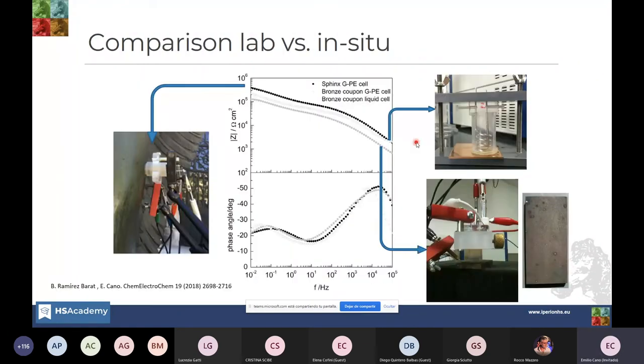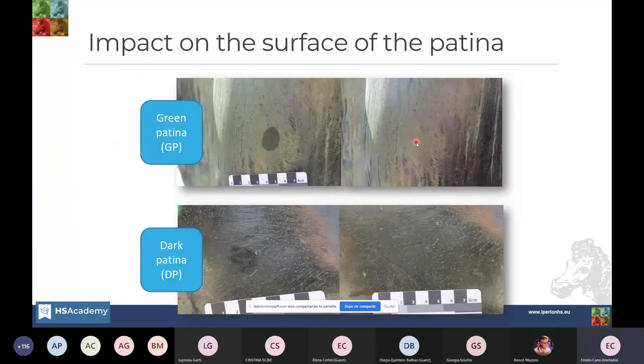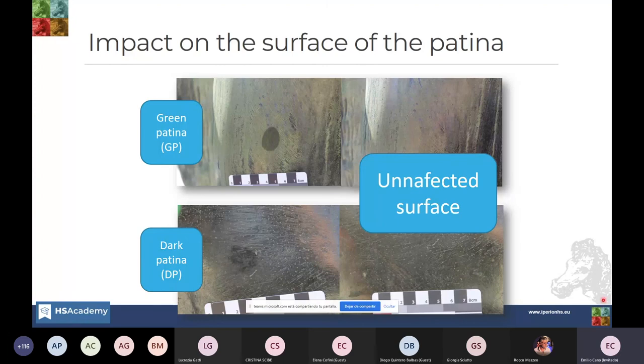I will skip these. We tested and we were sure that it left no residues on the surface. You can see this spot on the left is just after removing. The surface is wet, of course, because we applied that on the surface, but after a few seconds it is dry. And it left no visible residues. And I have to say that after almost 5 years, there is no visible effect on that.